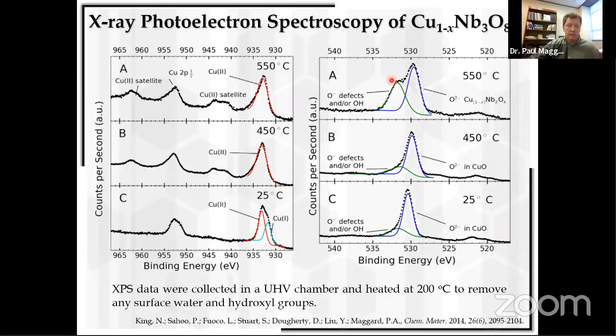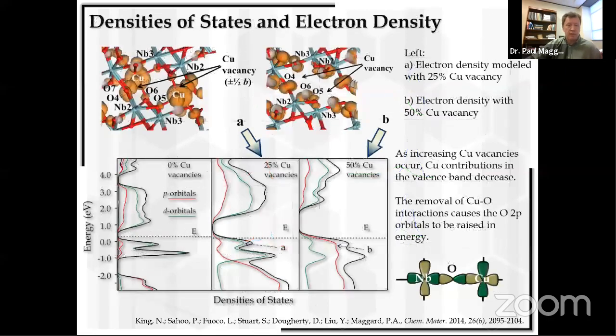the surfaces, right? So oxygen itself appears to be slightly oxidized, which was confusing for us because you would think it would only be copper 2+ being oxidized, or copper 1+ being oxidized to copper 2+. But given this evidence here, we took a closer look at the electronic structure to see what could be happening. And so within the structure of the 138 phase, we simulated it with full copper occupancy and no vacancies here, with 25% vacancies here, and then with 50% vacancies here.